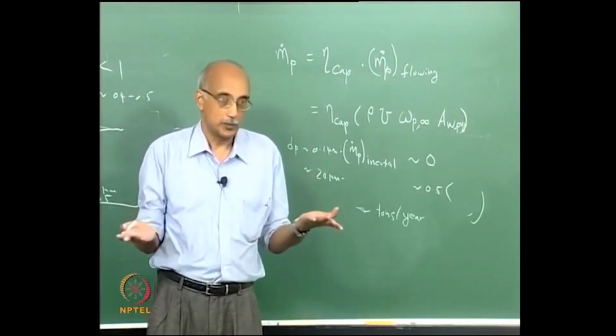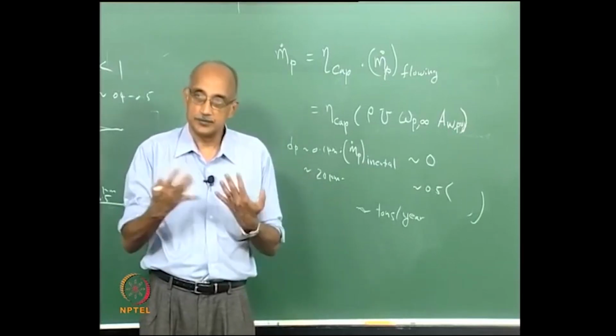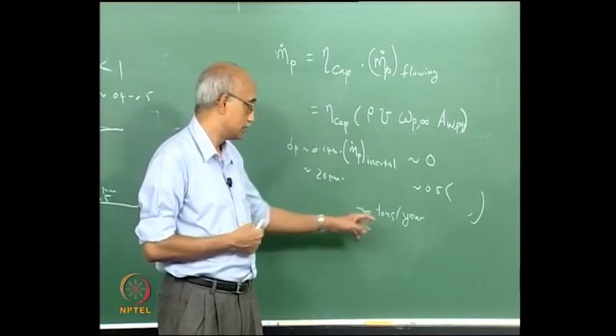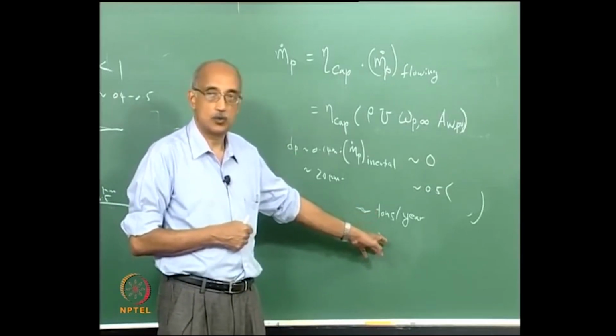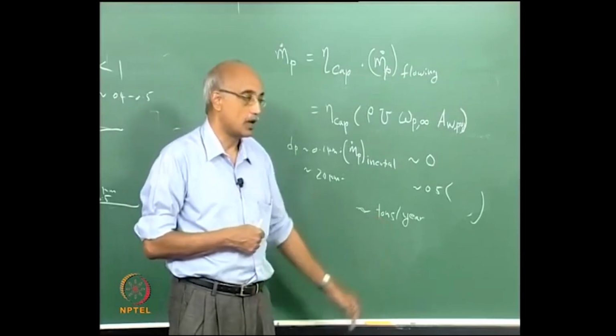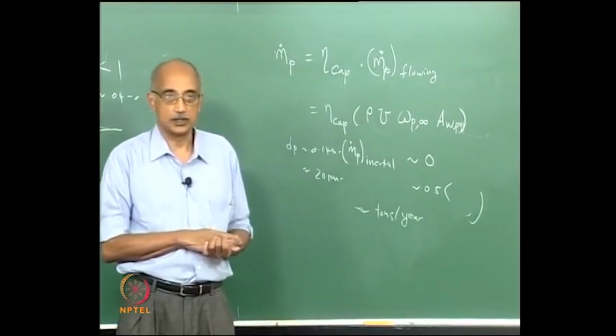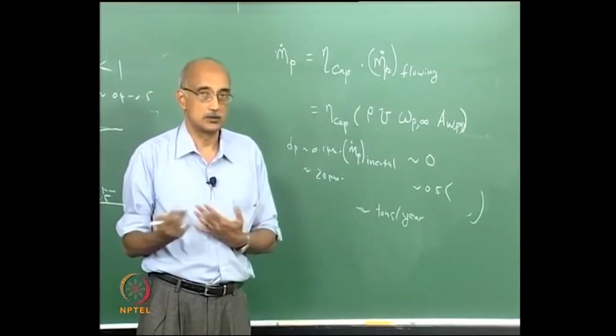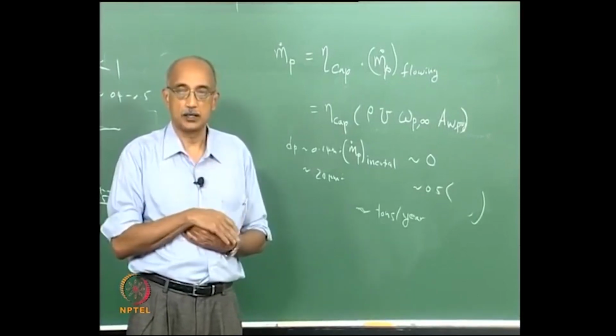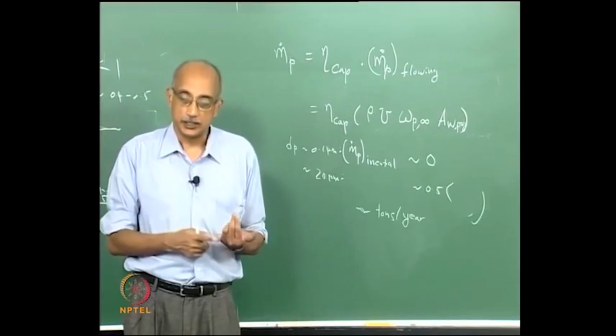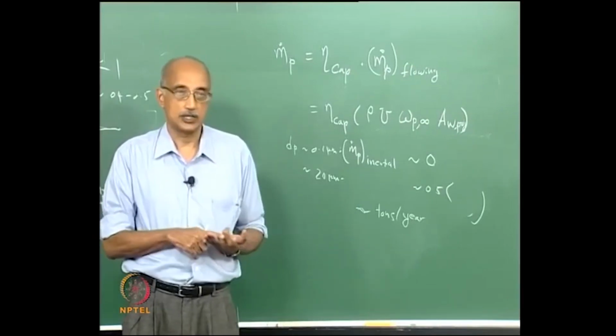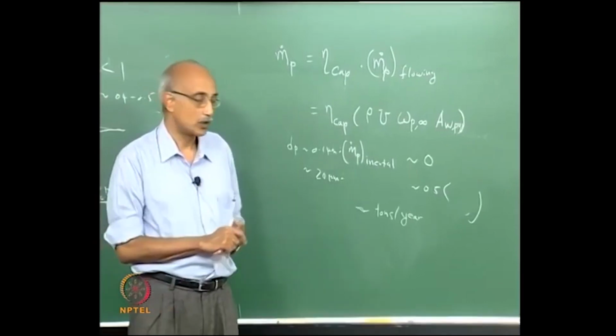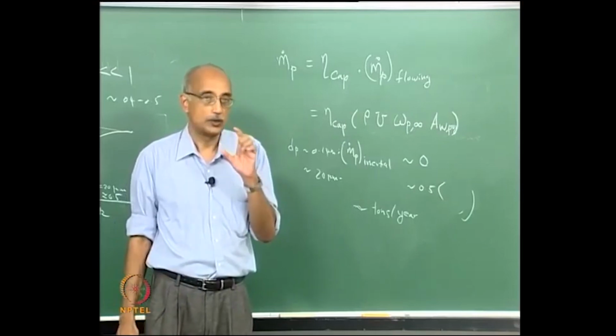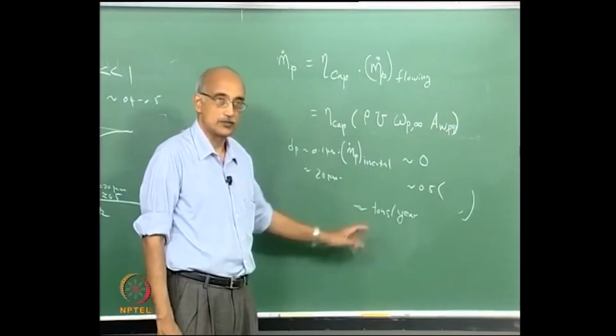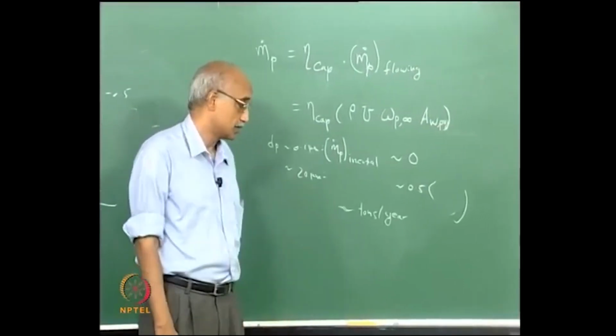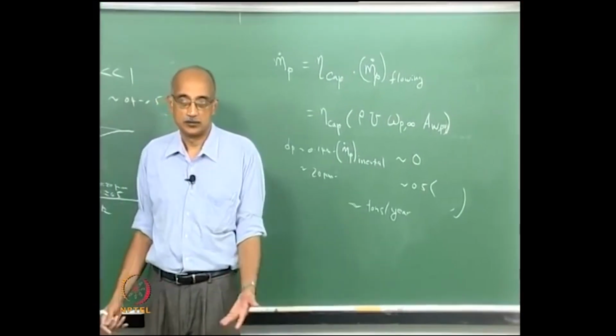So what do you do? You actually look at a power plant that is operating and try to get some data on what is the observed rate of deposition, and what you find is this is actually what is happening in power plants today. That is the reason why power plant losses due to fouling are such a huge problem in the industry. There are literally millions of dollars of loss daily on a global scale due to the fouling problem, because of the shutdowns required, the cleaning required, the reduction in heat transfer efficiency, the reduction in momentum transfer efficiency, all associated with the growth of these fouling deposits, which is directly related to this phenomenon. So this should give us some clues about how to extend the lifetime of boiler tubes.